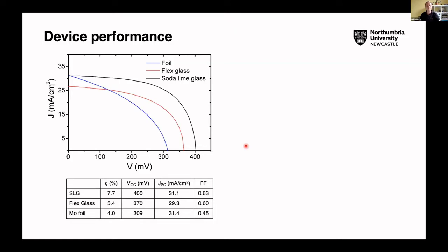And you'll remember in Martin's talk this morning, those 4 criteria. See if I can remember them: abundance, non-toxic, stable, I had them written down here, and the last one, efficiency. So that's our problem with CZTS, but it is a reasonably good candidate for coupling with silicon, as he mentioned. Then on the flexible glass, on Corning's willow glass, we have around 5.4%, and on the foil we have around 4%. And of course, the soda lime glass is the only one with any intrinsic sodium doping. So I'll say a little bit more about that in a minute.